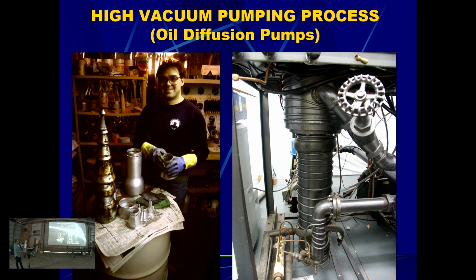So the oil basically hits the sides of the wall in here, and there's cold water going through this all the time. So the hot oil vapor, once it hits the inside of this chimney here, or the shower system, it's going to condense, and it rains down back into the pool of oil, and it recirculates. It gets reboiled, revaporized, recondenses, reboiled, and it keeps on going like that. And that's what brings it down to a high vacuum. As you can see, there's many parts to it. You can't have air ever seeing this oil vapor. Otherwise, you get soot build up on the aluminum. And it'll clog your nozzles eventually. You have to take the diffusion pump completely apart and clean it out.